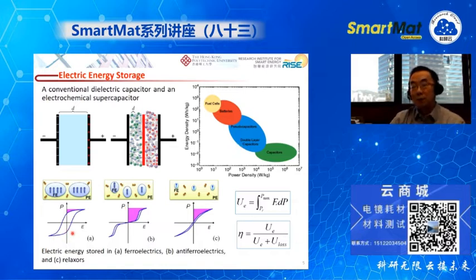And if we use ferroelectric material, as we just mentioned, when you apply an electric field, there will be a hysteresis loop being developed. So when you discharge, when you reduce the electric field, you can see the polarization does not go back to zero when all the electric field is removed. The released work due to the removal of the charge can be calculated by the integration of this shaded area. You can do this type of integration. So the energy release actually is the moving of charge on the external applied field. And from this figure, you can see due to the existence of the remnant polarization here, the energy release may not be very large.